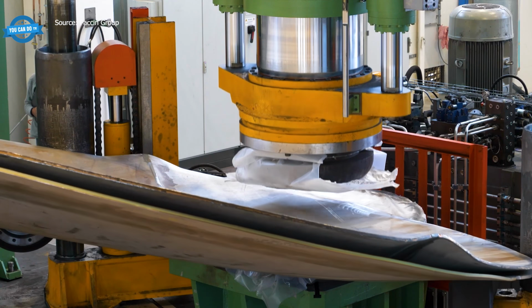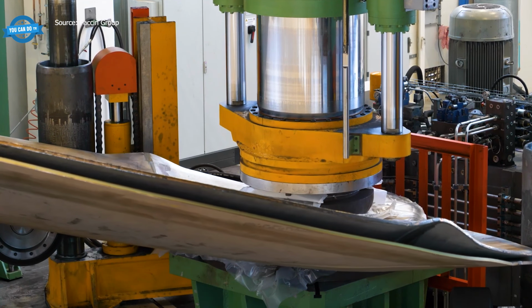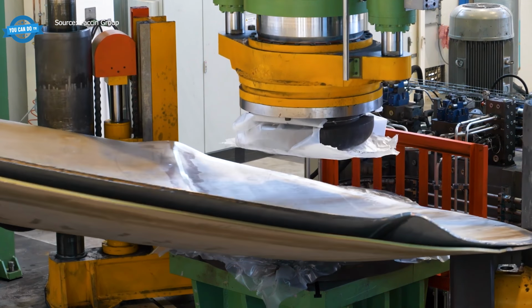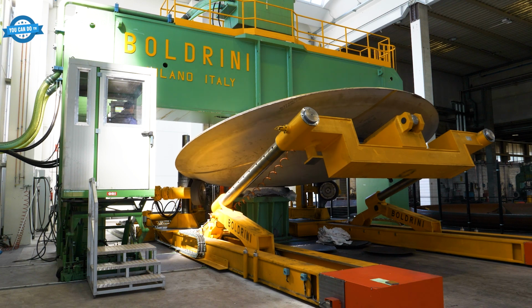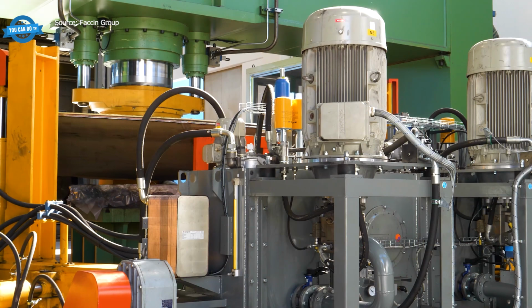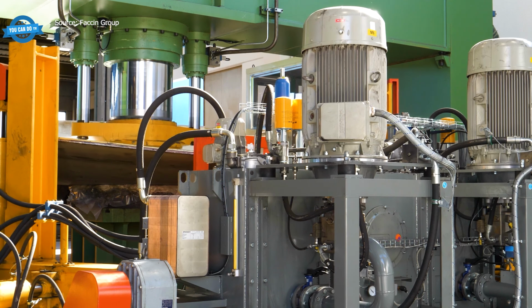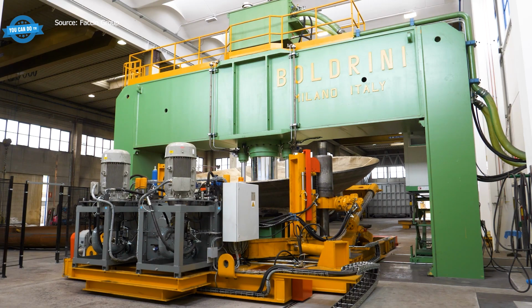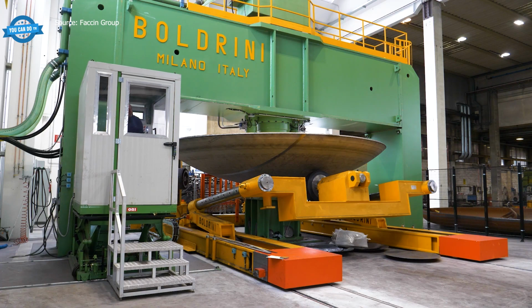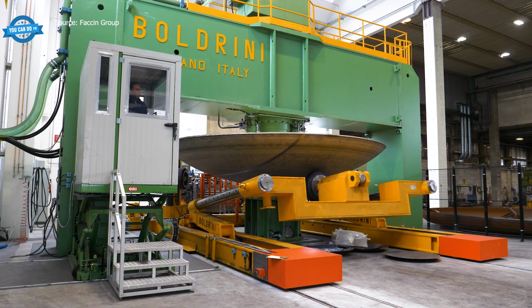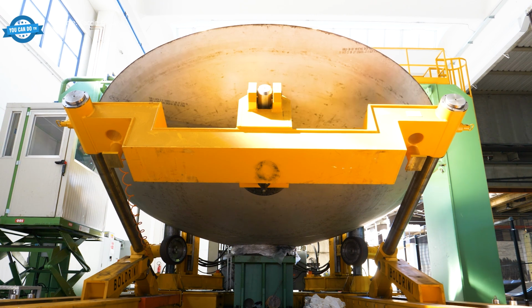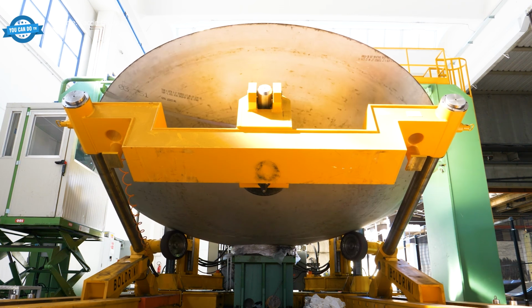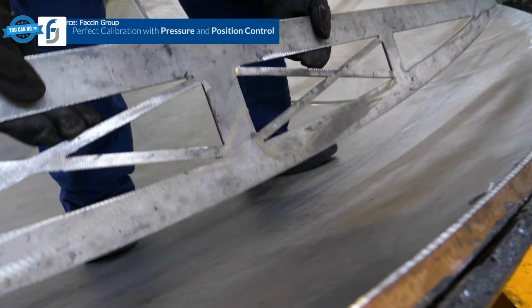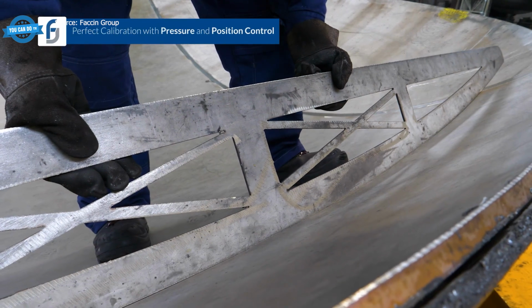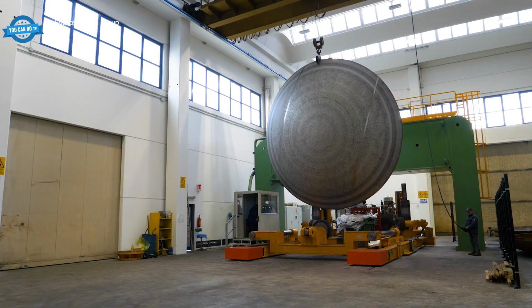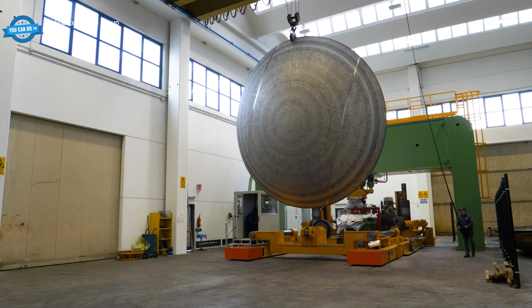Forming these massive curved heads takes machinery built specifically for the scale of offshore work. A portal frame press of 1,000 tons capacity handles cold blanks up to 9,100 millimeters in diameter and 90 millimeters in thickness, within a lifting limit of 27 metric tons, with a CNC manipulator for full automation. The press produces heads with smooth surfaces and a regular spherical profile, and surface smoothness directly affects corrosion life because every microscopic pit or roughness becomes a future starting point for rust under wet-dry cycling. The high-speed playback system allows exact, uninterrupted repetition of forming sequences, ensuring that every head in a production series matches the same protective geometry.